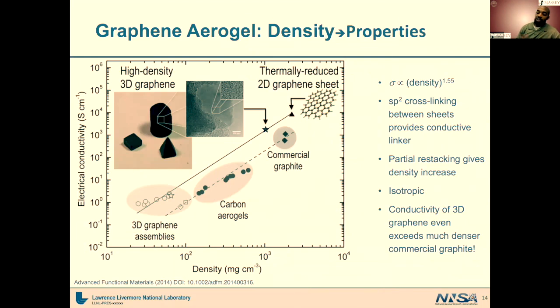One of the reasons, again, that we like working with the sol gel chemistry is that you can actually tune many of the properties by tuning the density. And so for most porous materials, mechanical properties such as stiffness or electrical conductivity are tied very, very tightly to the density. It actually is a superlinear sort of dependence. And so here, if you're looking at a log scale of your electrical conductivity as a function of density for both carbon and graphene aerogels, you can pretty much draw a straight line between low density as you move into higher density materials and track their electrical conductivity.